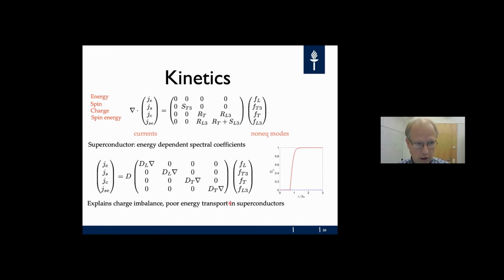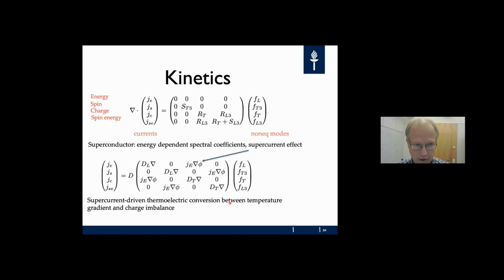You can also add a supercurrent. If you have phase gradients in the order parameter, you can add supercurrent terms here, and this fills up a little bit of this matrix. For example, it couples the FL and FT modes, a coupling between charge and heat mode, describing a supercurrent-driven thermoelectric conversion between temperature gradient and charge imbalance. This was already found in the late 1970s.